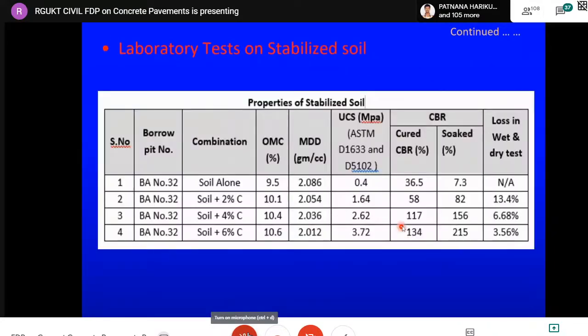Here you can see that even for 2%, I'm getting approximately 13.4% loss in weight in the wet and dry test. And for 4%, 6.68, and for 6%, 3.56.